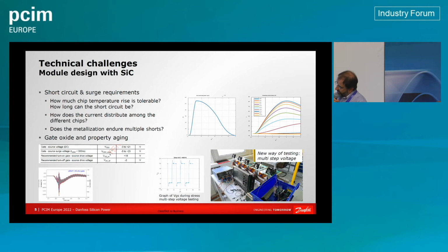In this case, what we have done is a multipolar stress tester. So we not only have, say, on and off, 2 voltages at which to stress the devices, like in the classical high temperature gate switching test, the HTGS, but in this case we have a 4 voltage one. You can see that in this waveform we go all the way down to -8 volts, then we relax it to -4, then switch on to +19 and then to +15. And we control the amount of time that we have of that gate source at each of the chips seeing a particular voltage or undershoot or overshoot, which is beyond the actual operating range.